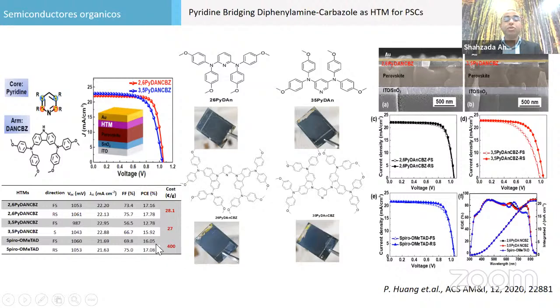The performance was close to Spiro, but Spiro was 400 euro per gram. This material is almost less than 30 euro per gram. We have calculated it, and there's no hysteresis, and the stability is also good.